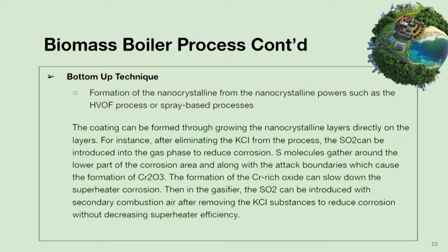The bottom-up method places emphasis on the formation of nanocrystalline coatings from nanocrystalline powders, such as the HVOF process or spray-based processes. Furthermore, the coating can be formed through growing nanocrystalline layers directly on other layers. For instance, after eliminating the potassium chloride from the process, the sulfur dioxide can be introduced into the gas phase to reduce corrosion. Sulfur molecules gather around the lowest part of the corrosion area and along the attack boundaries, which cause the formation of chromium oxides.